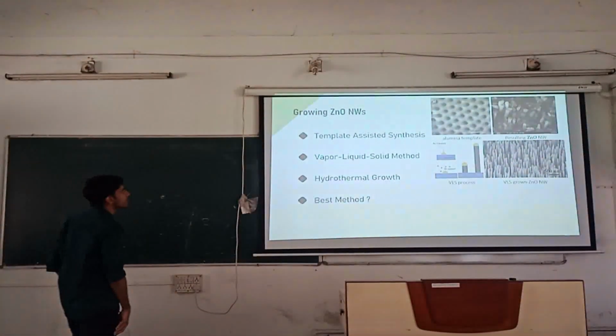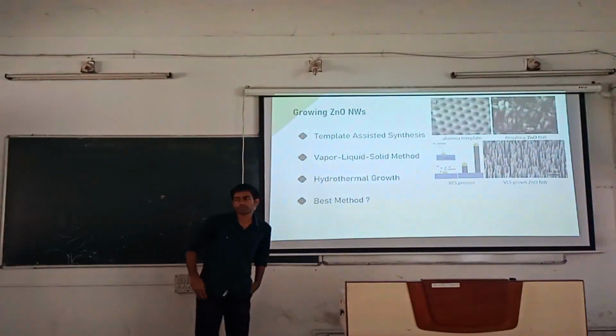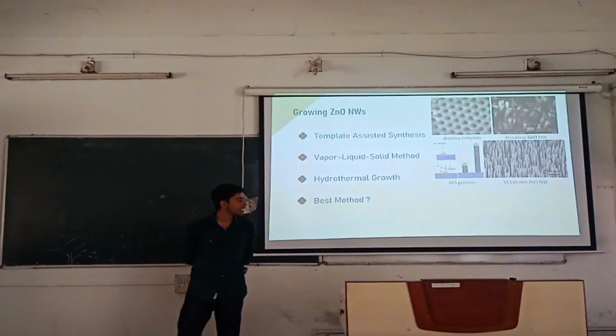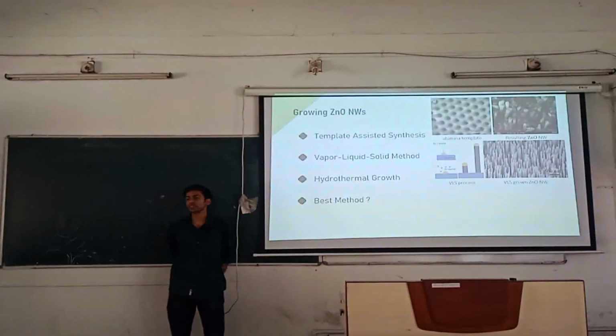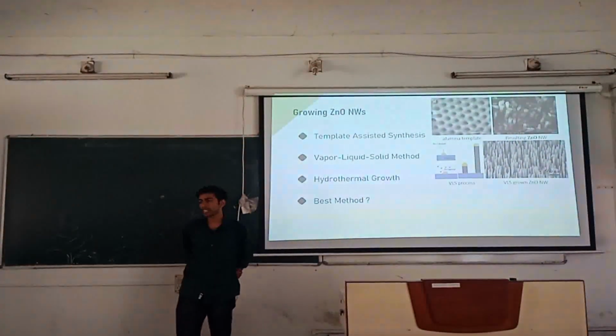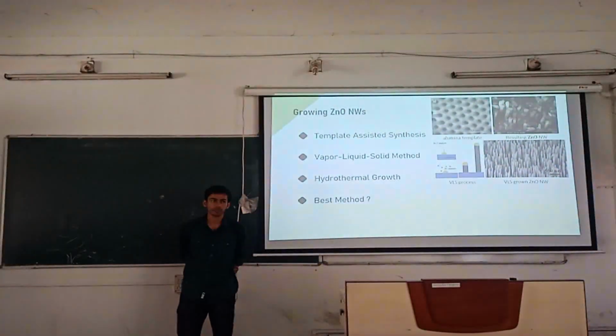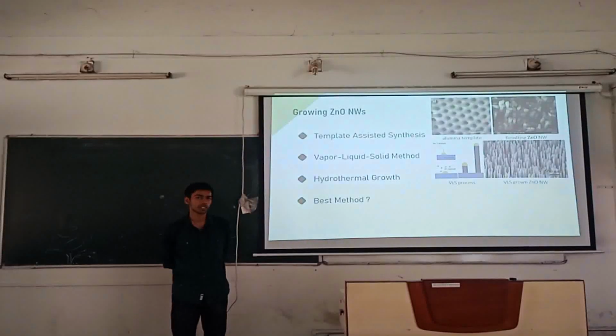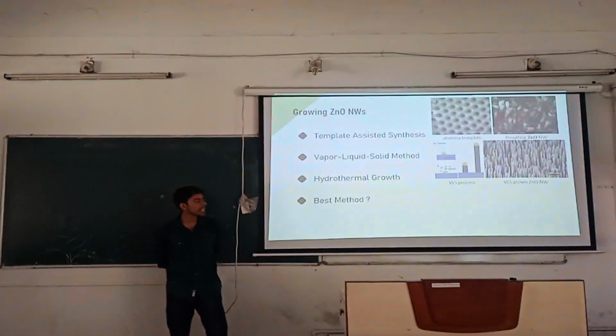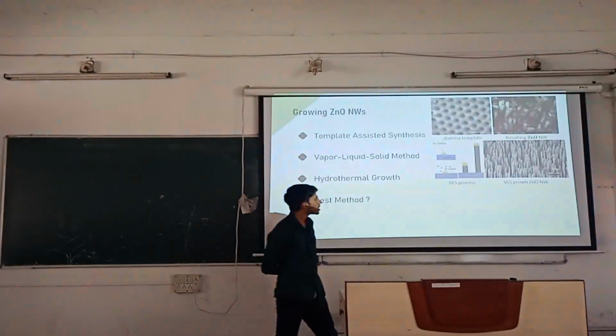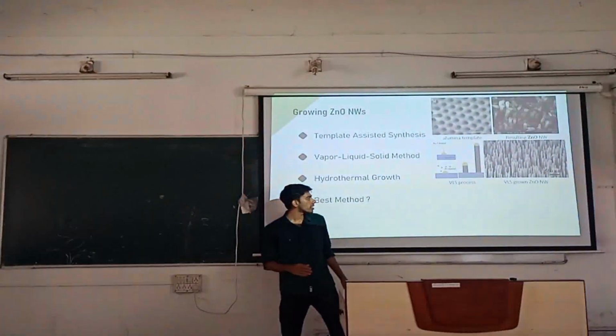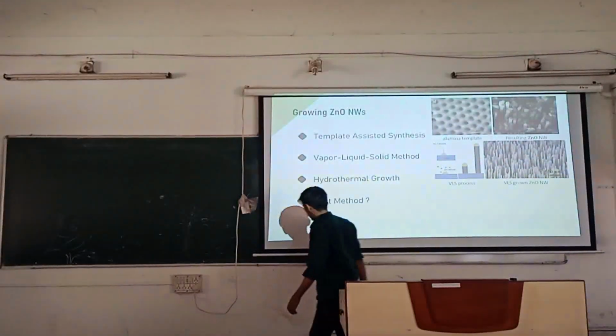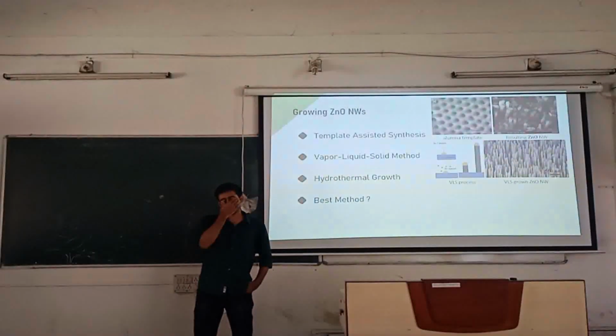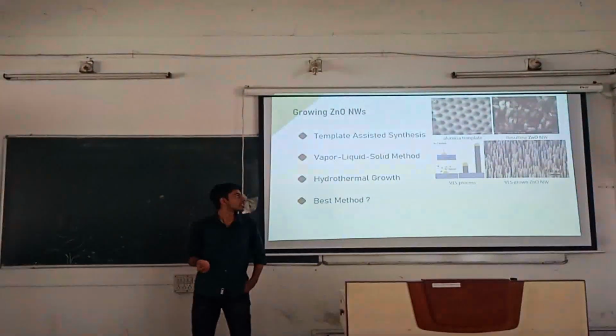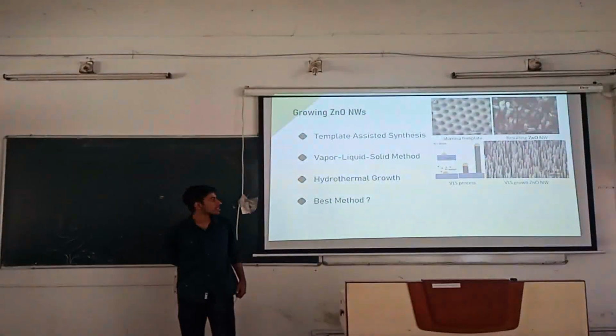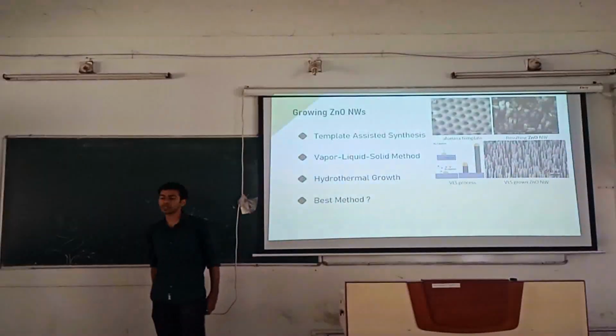Vapor liquid solid method is a very good method. But this is actually a very costly method. The idea is, if you heat zinc in presence of oxygen, in the presence of a catalyst gold, it will convert to zinc oxide. We want zinc oxide nanowires. So we use gold nanoparticles. We deposit gold nanoparticles on a surface, in yellow, and when we heat it in presence of zinc, growth will happen only at the place where catalyst is present. So the catalyst is nano, so the nanowire coming out will also be nano.